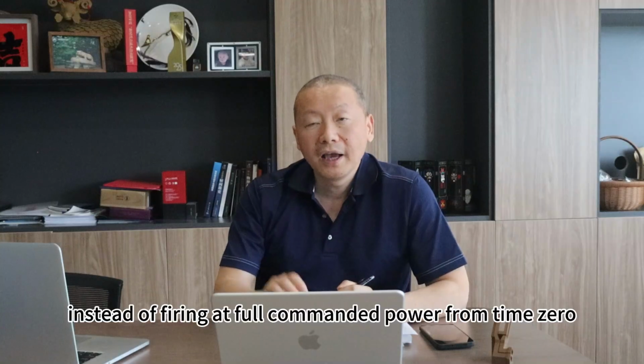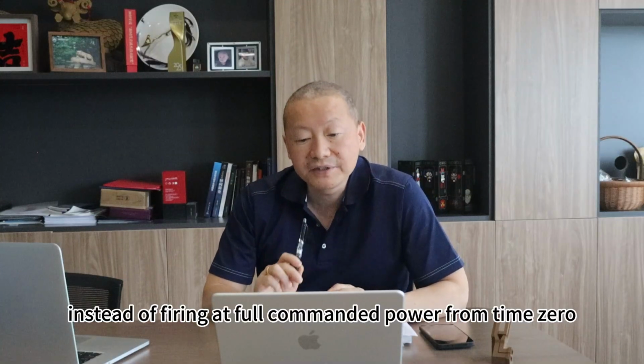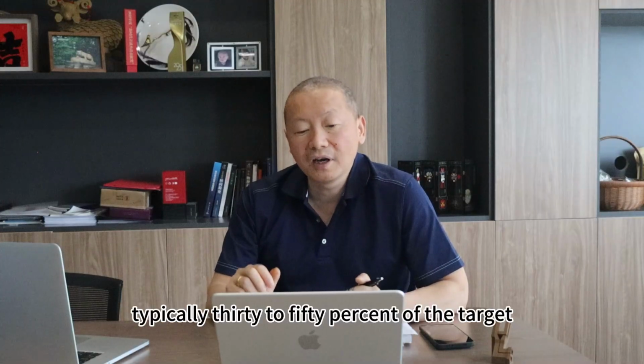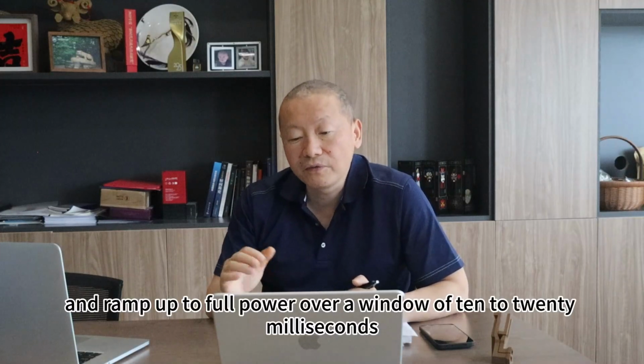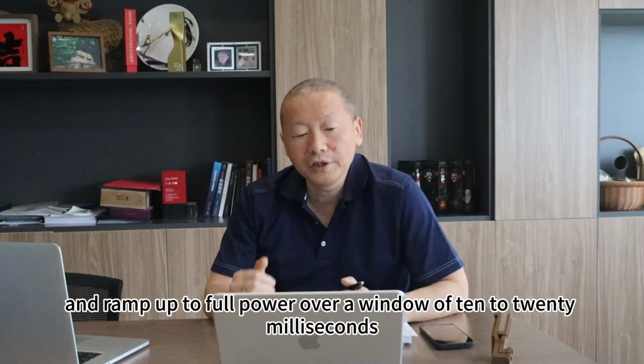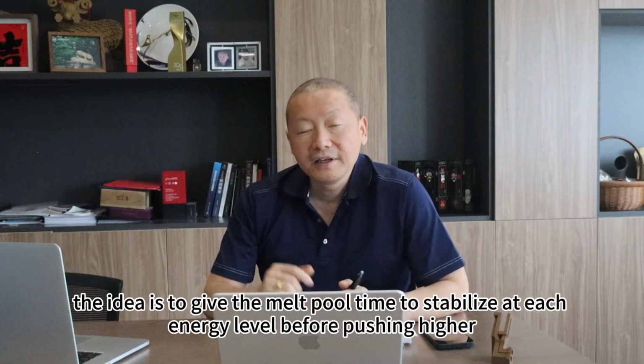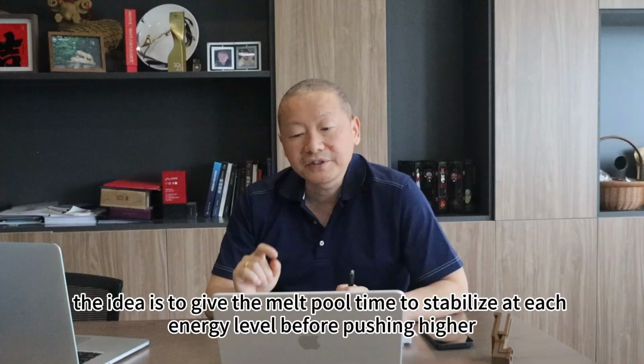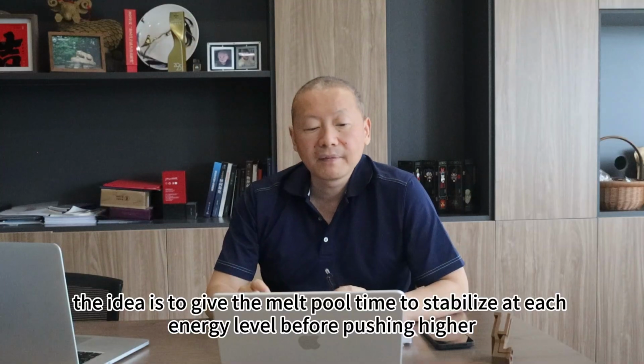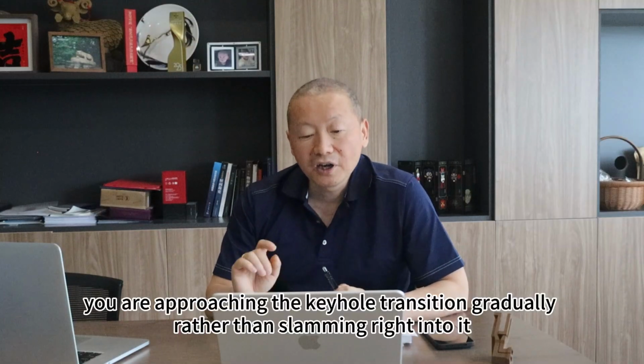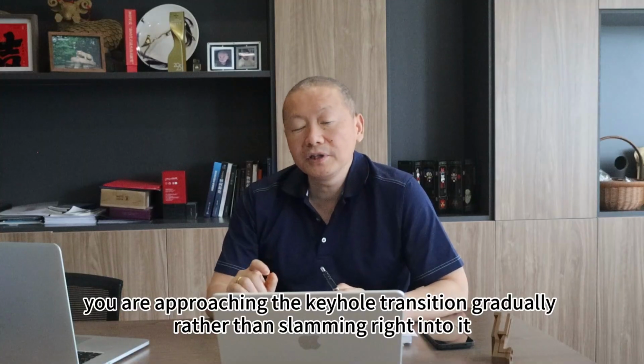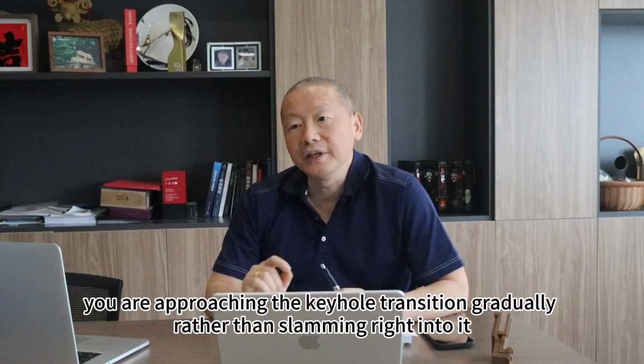Instead of firing at full commanded power from time 0, you start at low power, typically 30 to 50% of the target, and ramp up to full power over a window of 10 to 20 milliseconds. The idea is to give the melt pool time to stabilize at each energy level before pushing it higher. You are approaching the keyhole transition gradually rather than slamming right into it.